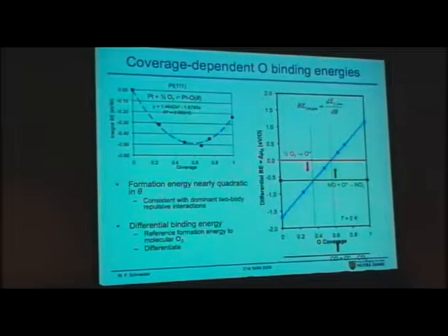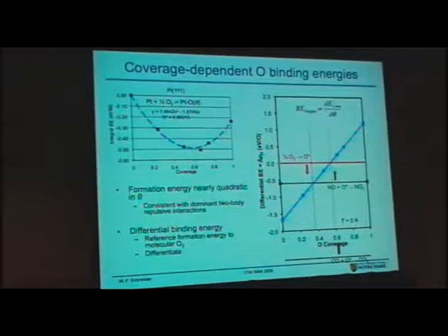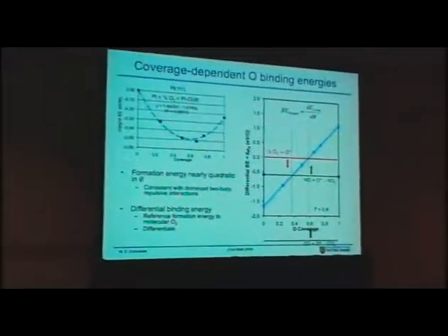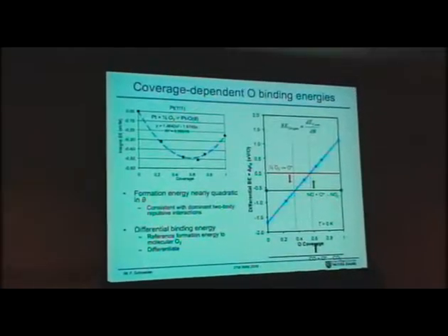One other thing I want to show on here. Here's the corresponding line for CO oxidation. You can see it's basically off the bottom of the chart. That's what I mean. CO is not selective, at least towards this particular surface. It'll pull oxygen off anywhere on here. NO is much more selective for the oxidation activity.